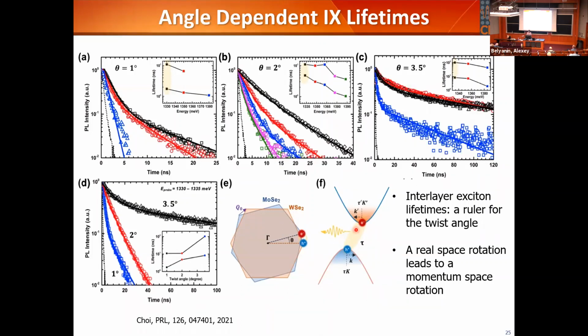Okay, so this is one of the mechanisms. The Moiré superlattice actually relaxes the momentum conservation requirement. If I only consider the band shifting, I would be looking at a lifetime change of 3 orders of magnitude. But with the Moiré superlattice, it only changes by 1 order of magnitude. So again, this has a profound change on the dynamics. That's related to the diffusion length.